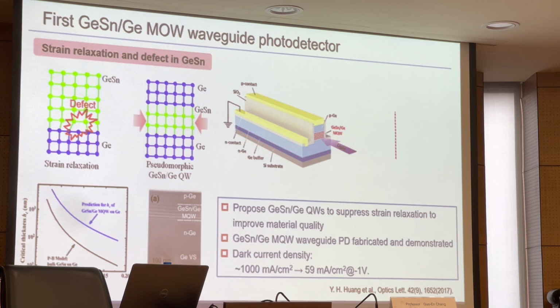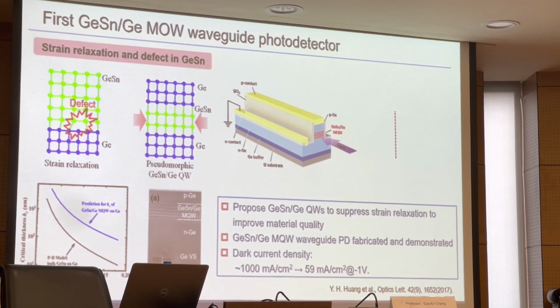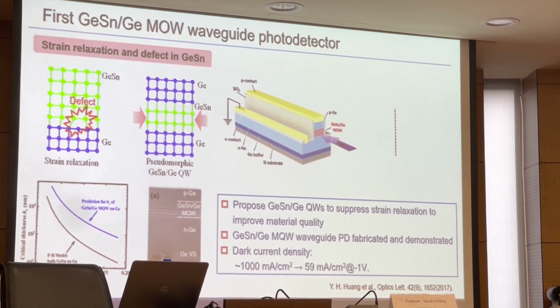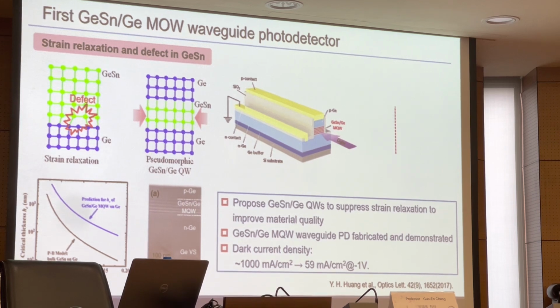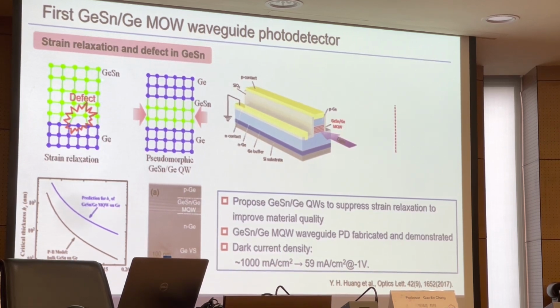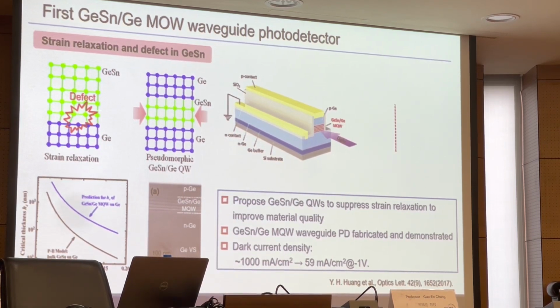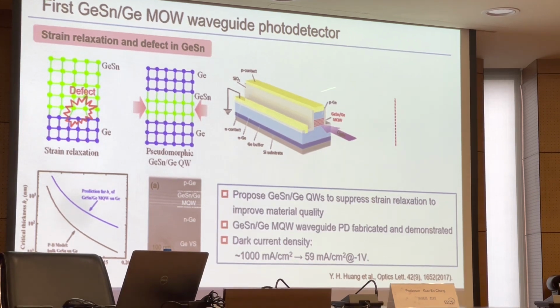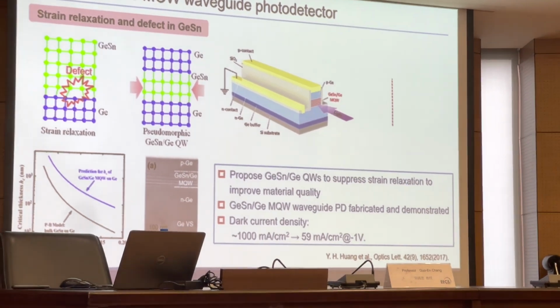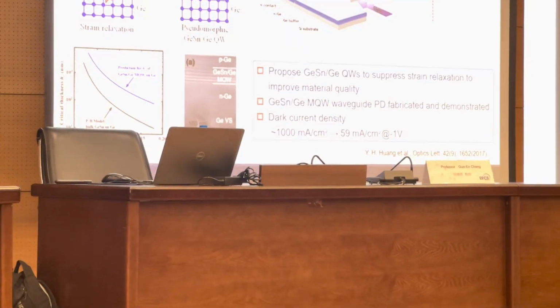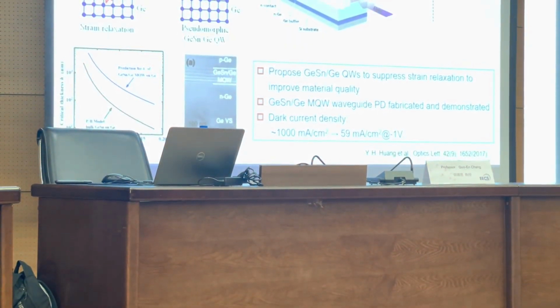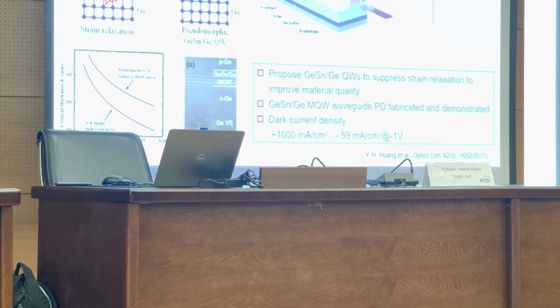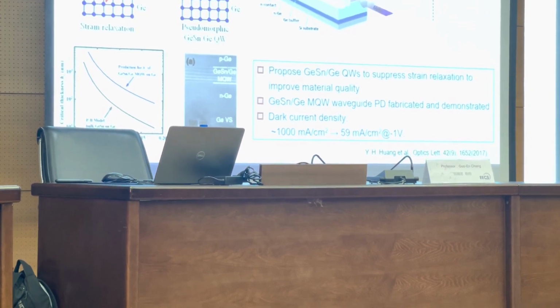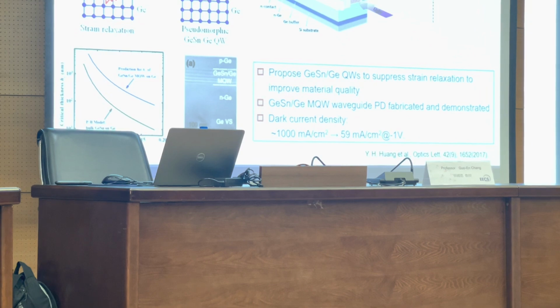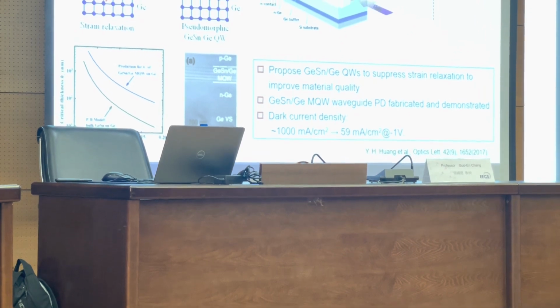Then we thought, how can we reduce the defect density? So we propose, instead of growing a thick germanium tin layer, we can grow a germanium tin quantum well. Because for a quantum well, the thickness can be very small, so we can control it to about 10 nanometers, well below the critical thickness. In this way, we can suppress the generation of defects.